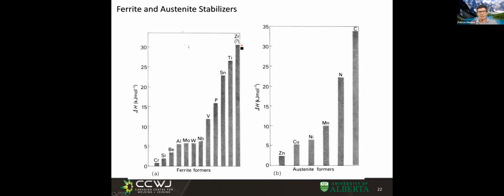We have, they put zirconium here, that is a lot, but we don't use much. Typically, zirconium gets trapped in oxides or carbides. We have titanium, tin, some impurities such as phosphorus, vanadium. Most of these are very strong carbide formers. All I'm trying to show you here is that when you start playing with alloying elements, you change your hardenability very much. And in showing you this, I'm showing you how some of these change one aspect of hardenability, that is the thermodynamic aspect.